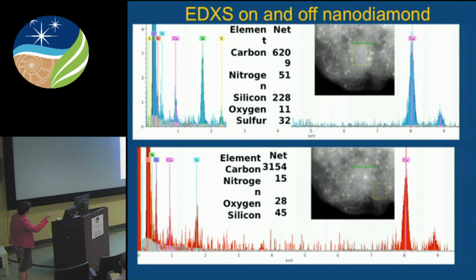So here you see the evidence that I work on a PC and not a Mac. So we've got the automatic scrolling. But anyways, we can make a measurement off of a 2 nanometer nanodiamond. So there's my sampling box right there, and you see that we have carbon counts, a carbon to nitrogen ratio different from bulk. So the nitrogen appears to be primarily associated with the nanodiamond.